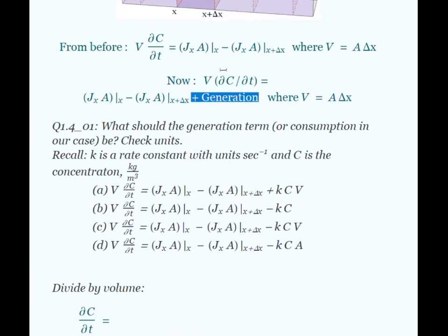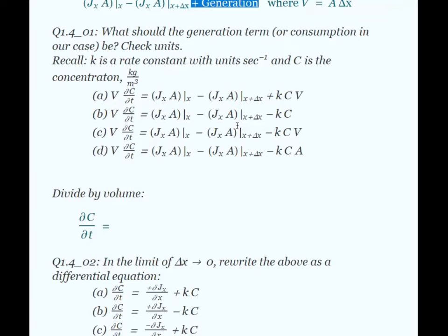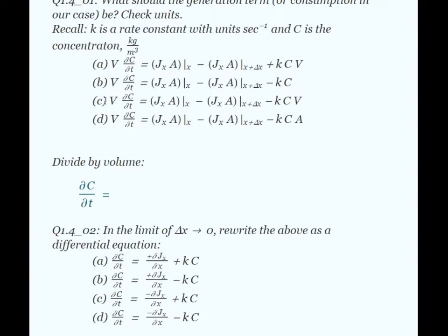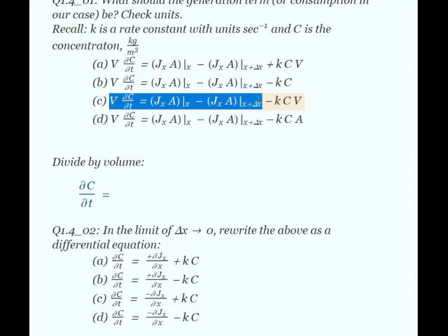Okay. And then again, the flux, a flux is kilogram per area per time. We multiply by the area so that this term is kilograms per time, kilogram per second. So we just have to make sure that those are all the same. So we've got the same formula that we had before in terms of our mass balance, and now we also lose K times C times V. So that's the number of kilograms of acetylene per second that is deposited out and therefore lost in terms of the concentration in the pores. So that will be the term that we use.